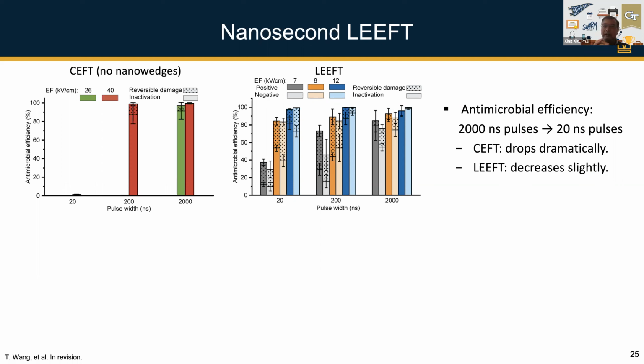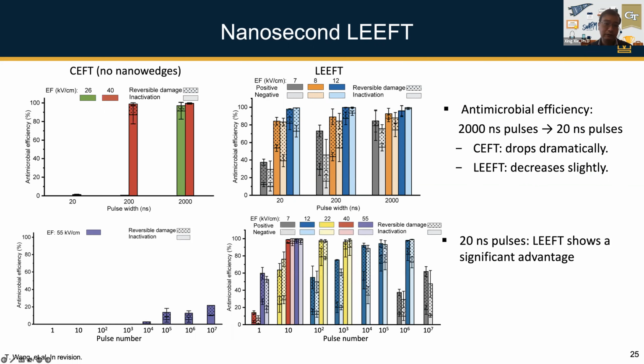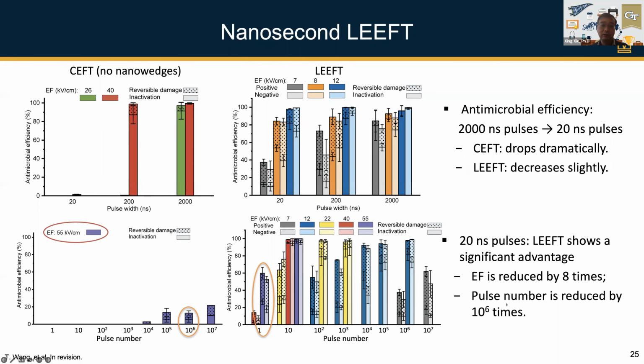So basically we noticed that with the LEEFT system, because the cells are very close to the electrode, there are different mechanisms behind it, so I won't be able to go into a lot of details, but I want to show you the result. If you compare this LEEFT process to the conventional electric field treatment, you can either significantly reduce the voltage applied, about 8 times, from 55 kilovolt per centimeter to only 7 kilovolt per centimeter, and the inactivation efficiency is even higher, or you can significantly reduce the time required for the electric field treatment.